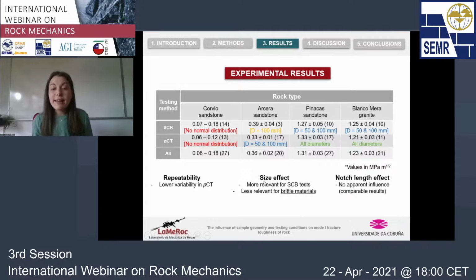We can also detect that there is a size effect, which seems to be more relevant for the SEV than for the PCT, because, for instance, here for the SEV, we had to discard all the values for the smallest specimens, and the size effect seems to be less relevant for brittle materials, surprisingly. And for the Pinacas and Arthera sandstone, which are the harder materials, all the 3 specimen sizes that we have tested conform to a normal distribution.